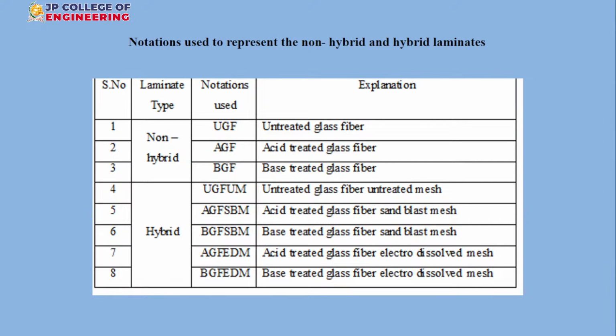So we made almost 8 different varieties of the composites. 3 non-hybrid: only untreated fiber, then acid treated, and then base treated fiber. And then 5 different varieties with the stainless steel wire mesh, with different kinds of surface treatment. So all 8 items are tested.